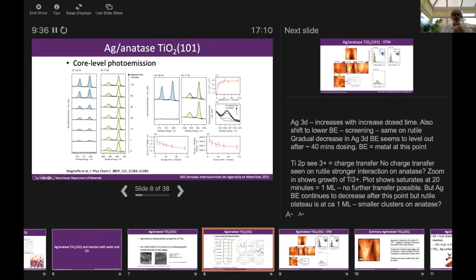So we first started off doing some core level photoemission. This is the silver 3d core level spectrum. As you can see, as we increase the silver exposure, we get an increase in intensity, as you expect. The titanium 2p is interesting because we see this small shoulder. This is a zoom in of this region. So we see as we increase the silver coverage, we get this additional peak appearing in the titanium 2p. And this peak is associated with the reduction of titanium from Ti4+, which you would expect in TiO2, to Ti3+. So it's suggesting that there's some partial charge transfer into the titanium dioxide surface.